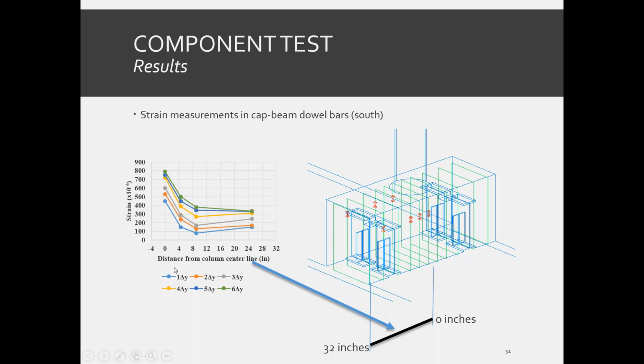The results show that the maximum strain occurred near the column. The maximum observed strain in these dowel bars is almost 800 microstrain, which is much below the steel yield strain.